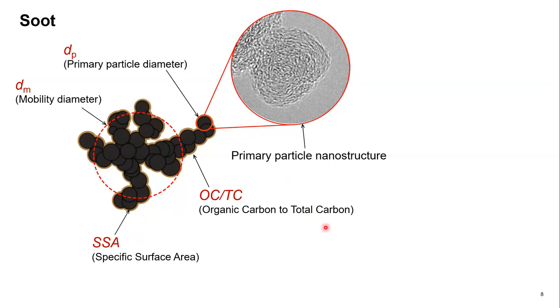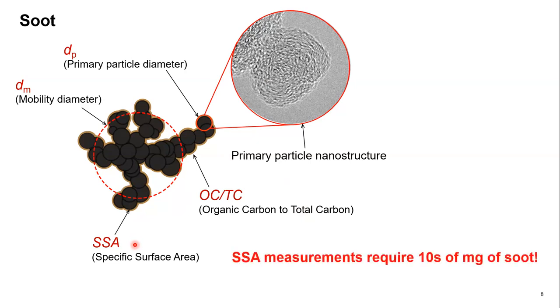These other parameters that I've specified are routinely measured in the aerosol science community. However, the specific surface area is not routinely measured despite its important implications. And this is because specific surface area measurements require tens of milligrams of soot. This amount of soot is very difficult to obtain. It's nearly impossible to obtain directly from the atmosphere. And even when we're performing engine tests, it would be very costly to run the engines for long enough to obtain this amount of soot, and certainly not to do it routinely.